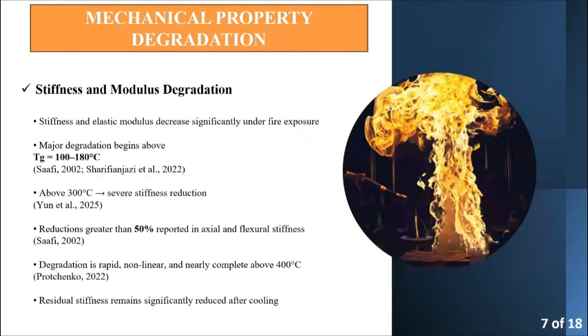Now let's move on to understand how fire affects stiffness and elastic modulus in FRP-reinforced concrete. Stiffness is very important because it controls how much a structure bends or deflects under load. You already know that the elastic modulus represents the rigidity of the material, right? When the temperature increases and reaches the glass transition temperature, between 100 and 180 degrees Celsius, the resin inside the FRP starts to soften. When this happens, the material becomes less rigid. As a result, the elastic modulus decreases and the structure becomes more flexible.